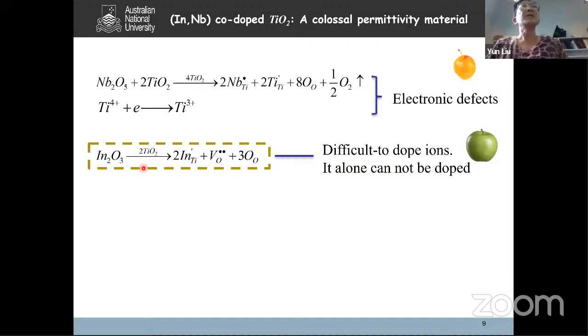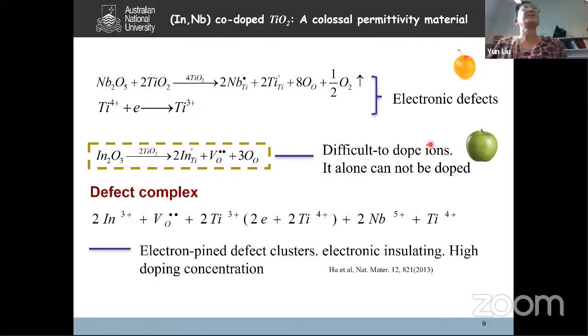Like 0.1%. However, if we have niobium here, they can synergistically interact together. Actually, we can form defect clusters. As you can see here, if these two extrinsic ions integrate together, you can create a defect complex, which not only has electrons but also vacancies, and this defect cluster is very big. It's related to 7-8 octahedra.